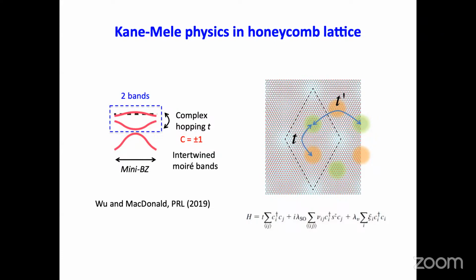Okay. So Bill, another way of thinking about it is that if you didn't have Moiré and you look at the original system, those hopping matrix elements t will be on the order of an electron volt. And it has come down to the order of millielectron volts. So it has suddenly flattened a lot, and this comparison that I talked about makes it flat. But it's not exactly flat, because for exactly flat, it should be zero, the mass should be infinite. That's not going to happen. Okay.